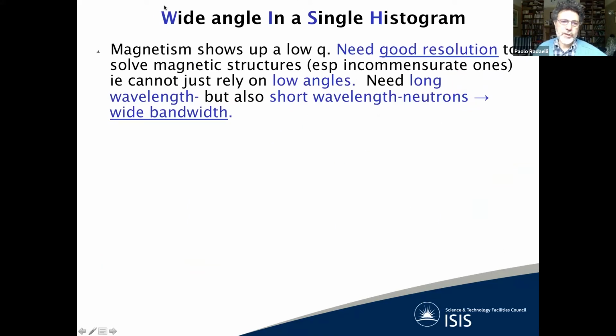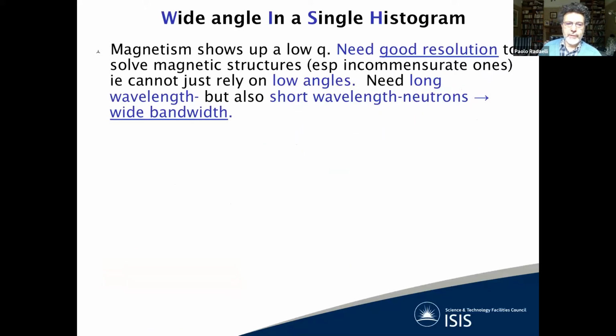So WISH stands for wide angle in a single histogram. And we were thinking primarily at magnetism, and the intuition was contrary to what most people were thinking, actually, that we needed good resolution to solve magnetic structures, especially incommensurate complex magnetic structures. So we can't just do low angles. And the pattern I showed before is a clear illustration. This is not even that complex a magnetic structure, but there is clearly much better resolution in the kind of 7-8 angstroms range.